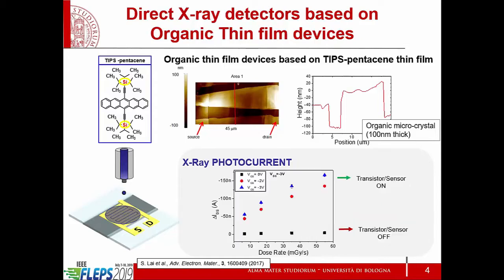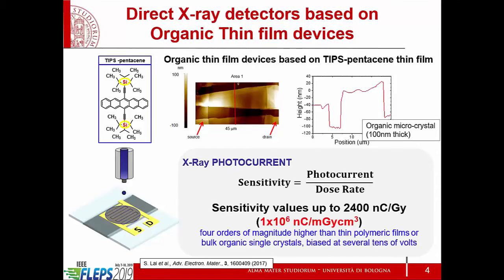Why is there an advantage of using a transistor? Yes, the advantage is that you can control the on-off state of the sensor. So basically, by controlling with the gate voltage, you can switch the sensor off, or you can switch it on and increase the sensitivity because you control the amount of carriers in the channel. In this way, we manage to obtain sensitivity values that are very, very good compared to the standard values for polymeric films that have been added with nanoparticles, or even with organic single crystals that need to be operated, though, at several tens of volts.